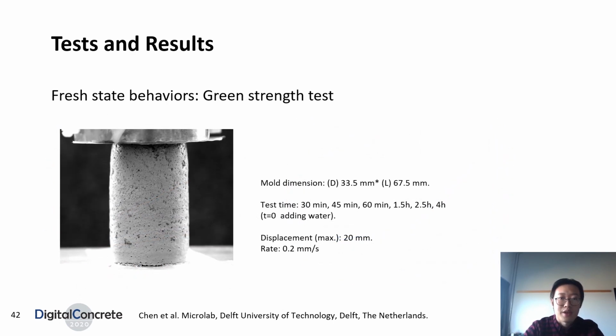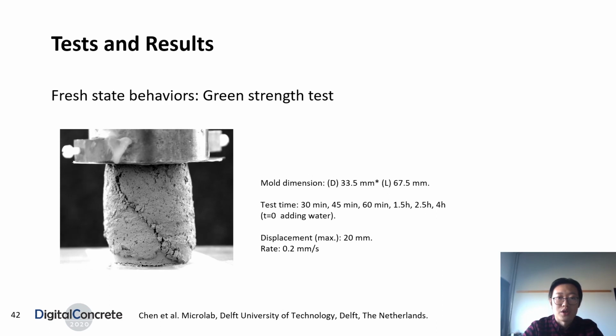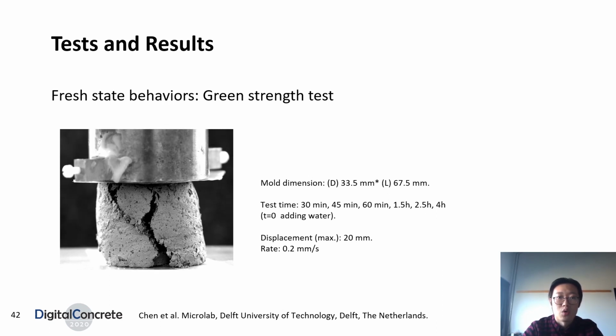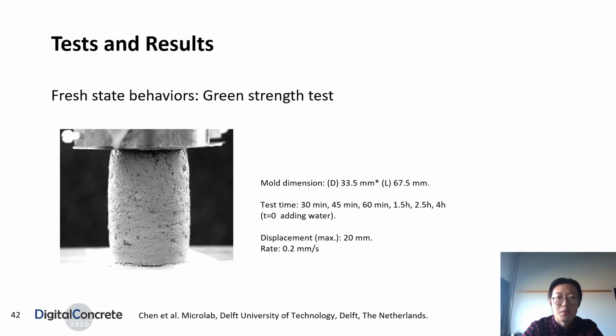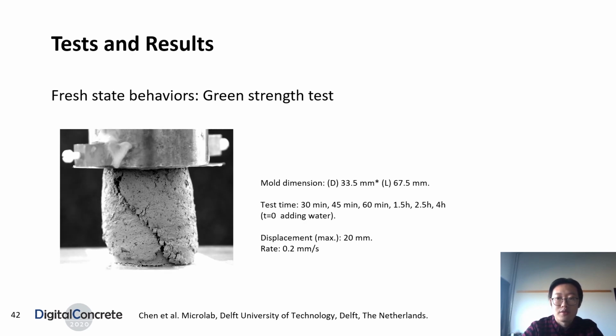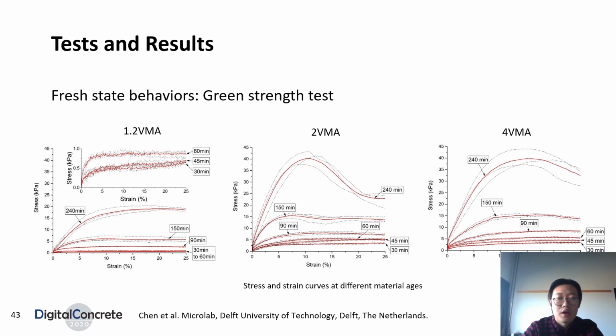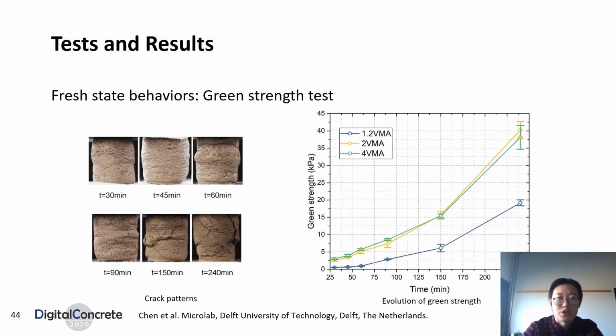The last test in this aspect is the green strength test. Small cylinder samples were tested at ages from 30 minutes to 4 hours. The true stress and strain curves of different mixtures at different material ages are illustrated in this figure. Mixture 2 VMA shows a very close green strength compared to 4 VMA, and both of them are much higher than 1.2 VMA.